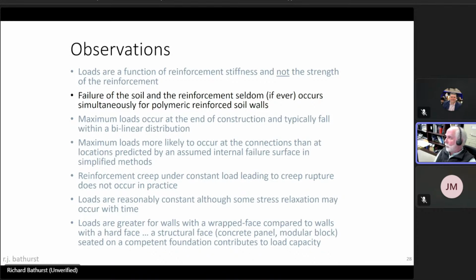Another observation that we were able to make is that the soil and the reinforcement seldom simultaneously failed if you surcharge these walls heavily. And this is in contrast to concepts of limit equilibrium, where reinforced systems are assumed to generate their limiting strength under the same conditions. This was not observed in our tests, and I can show that in the next slides.